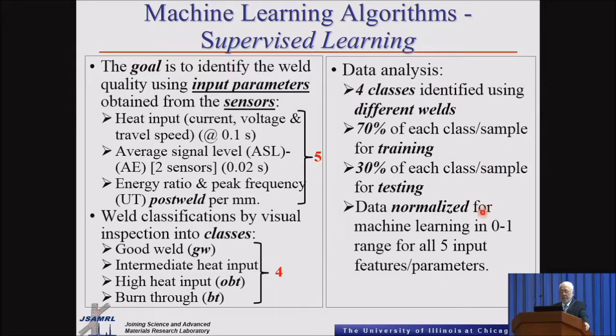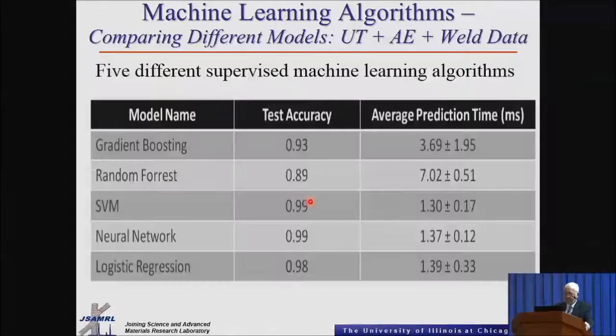70% of all the data collected was used for training of the machine learning algorithm, and the other 30% was for testing. The data was normalized for machine learning in a 0 to 1 range for all 5 input features or parameters. These input features were obtained from the sensors.